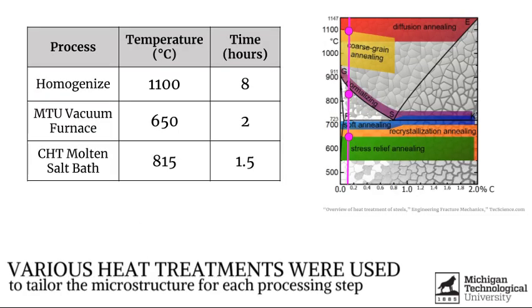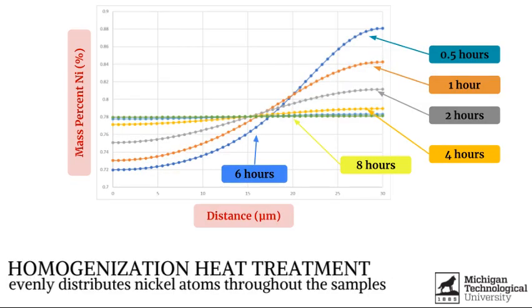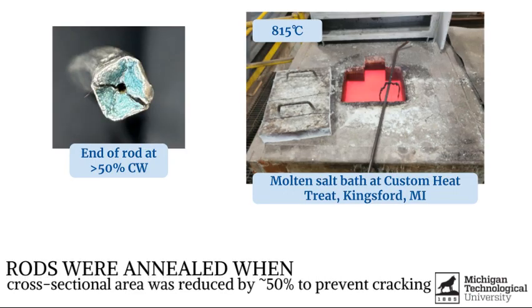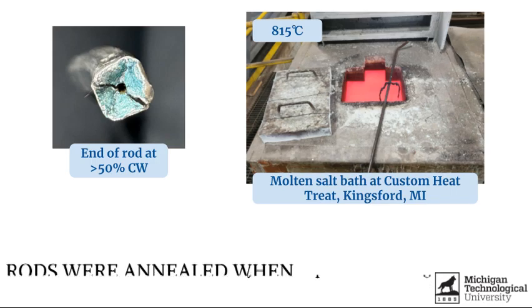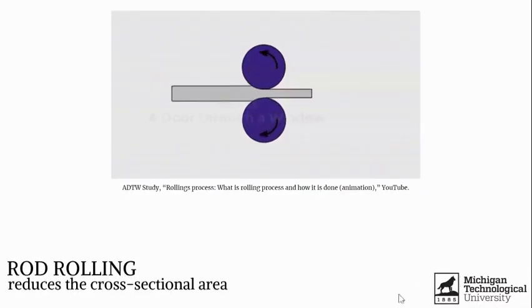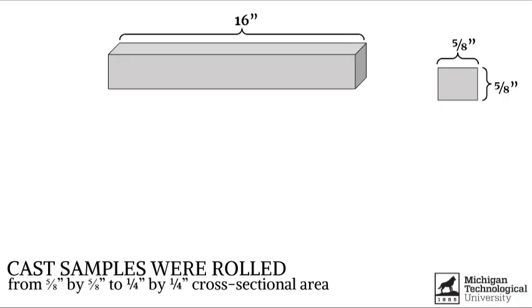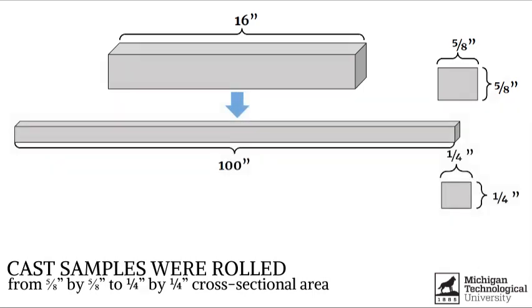Multiple heat treatment methods were used throughout the process to ensure homogeneity and proper strain relief for processing. The homogenization time and temperature were determined using ThermoCalc simulation software based on diffusion rate of alloying elements. Annealing was used throughout rod rolling and swaging to relieve strain due to work hardening and prevent material failure. Rod rolling uses compressive force between 2 rollers to reduce the cross-sectional area of a sample. This process was used to bring our 16-inch bars with a cross-sectional side length of 5/8 down to a side length of 1/4, which resulted in approximately 8-foot-long bars.